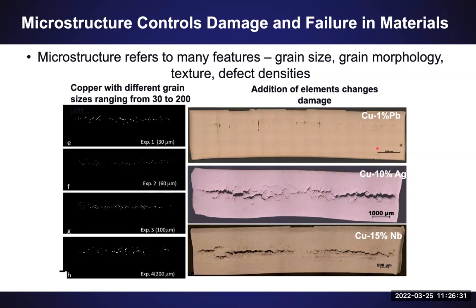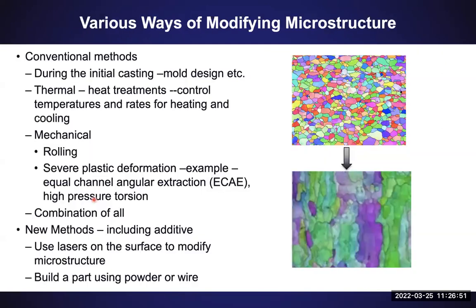If you add other things, like if you alloy copper and repeat similar experiments, here's an example on the right showing that if you added lead versus silver versus niobium, it changed the microstructure that you had and basically changed the total amount of damage in the sample. So we know microstructure controls damage and failure. We want to design materials for extreme conditions. So one easy thing that we can do is control our microstructure.